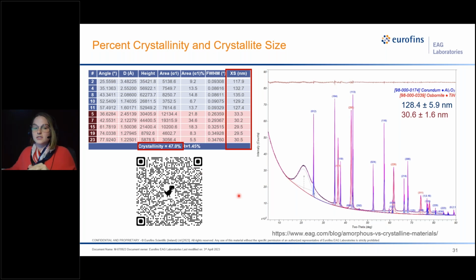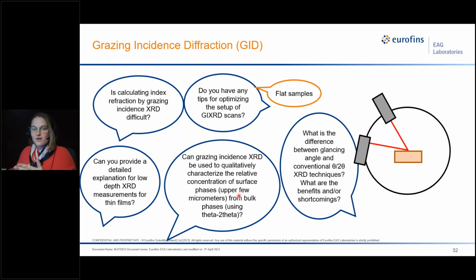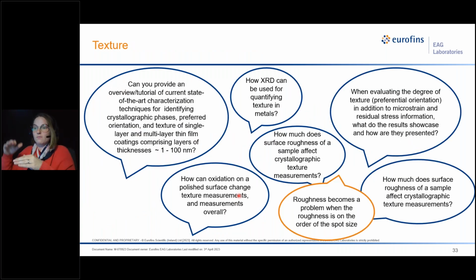This QR code is actually a blog post that EAG did explaining more about what's crystalline and what's not crystalline, for future reading. A lot of people want to know, can I analyze just the top surface of my sample? And the answer is yes. This is called grazing incidence. So we have a fixed incident angle, but we scan over 2 theta. Because we know the incident angle, and if you know the density of your material, you can calculate how far into the sample you're penetrating.